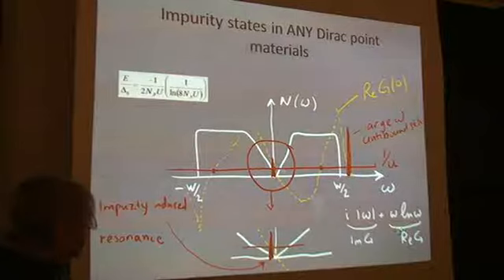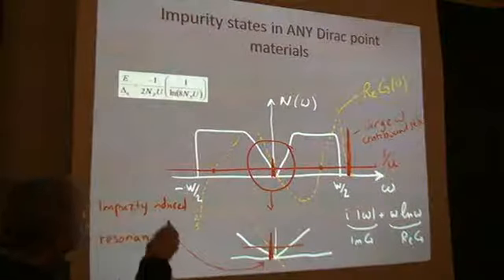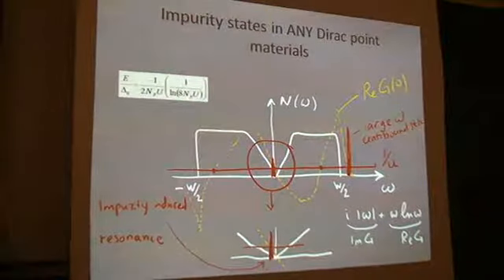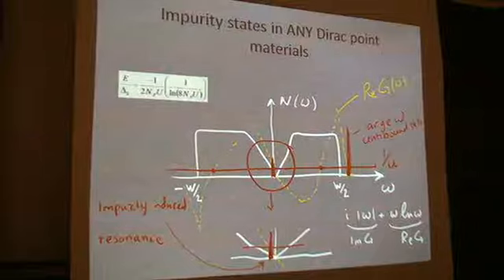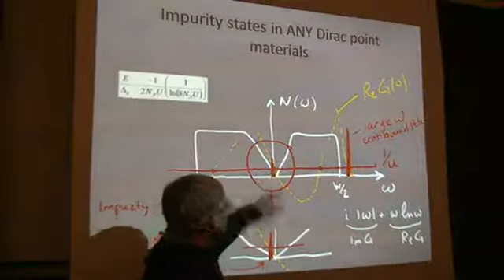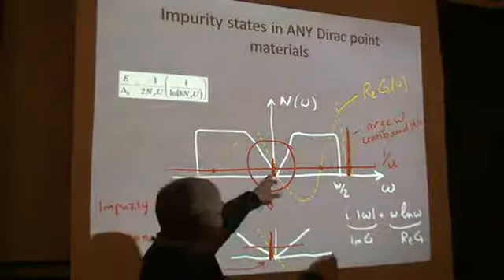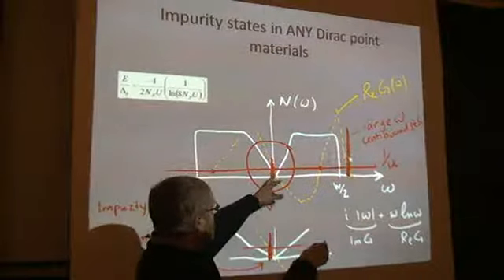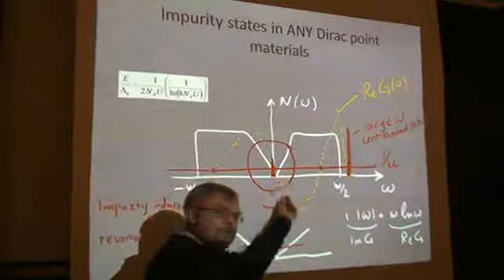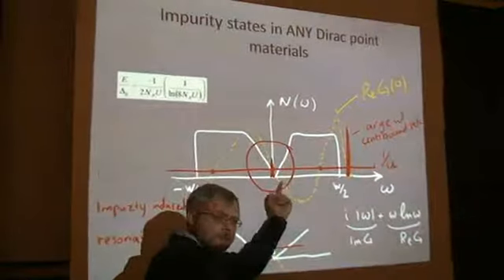And so you solve this. Omega log omega is equal to 1 over U. You iterate, you get this. It's very simple. Now, this and this are Kramers-Kronig relations. So this one knows about this one and the other way around. It's only because I pulled the density of states here that there is a little spillover effect.